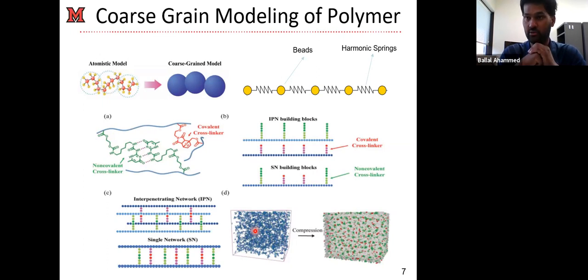What percentage of them is crosslinked? But we allow sufficient time and temperature to get crosslinks. When we are satisfied, looking into the structure, it seems they're crosslinked. Then we start compressing the system, like you compress the shape of your simulation box, because you need to attain the desired density. In our case, it is the density of water, 1000 kg per meter cube. So we compressed our simulation box or the volume fractions until we reached our desired volume fractions. When you reach them, you stop compressing. So that is our sample.